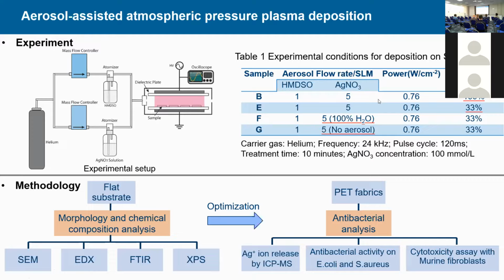Accordingly, we optimize the experimental condition and further use PET fabrics as substrates in the deposition for biomedical applications. We check silver ion release with ICP-MS, and antibacterial activity with gram-negative bacteria E. coli and gram-positive bacteria S. aureus. We also check the cytotoxicity with murine fibroblast cells.